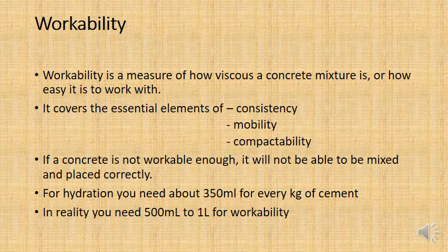So remember that the hydration reaction I talked about before with tricalcium silicate, tricalcium aluminate and dicalcium silicate, for that hydration reaction to work, you need to have about 350 mils of water for every kilogram of cement. That's the ratio you need roughly.